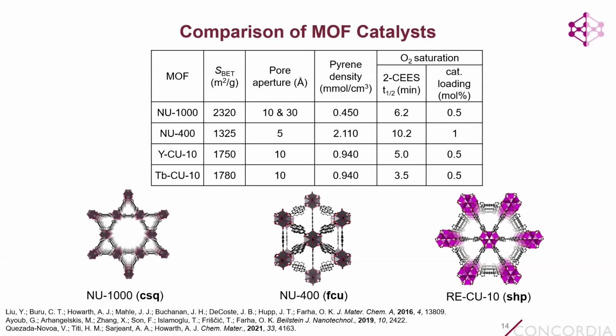If we look at NU400, this has a very small pore aperture size, so not very good for the diffusion of reactants and products, but it has a high density of pyrene chromophores, ultimately giving rise to a pretty slow half-life. But if we look at Cu10, it has this kind of balance between pore aperture size and pyrene chromophore density, where we have this moderate pore aperture size, so not too bad for diffusion, this moderate density of pyrene chromophores, and ultimately giving rise to these faster half-lives that we see.